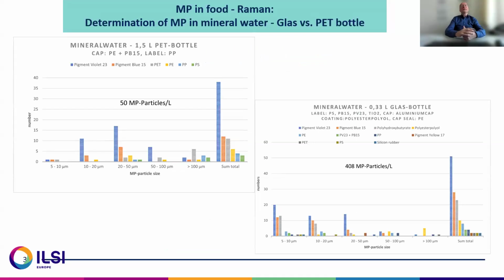Then we investigated a lot of mineral water in glass, PET, Tetra Paks and so on. Here is a comparison between a PET bottle and a glass bottle, because the bottles had a different filling. We extrapolated it to 1 liter. So you can see in the PET bottle we have 50 microplastic particles. However, double of the particles are pigment particles, because the pigments are used also for the labels and for the printing of the bottles.